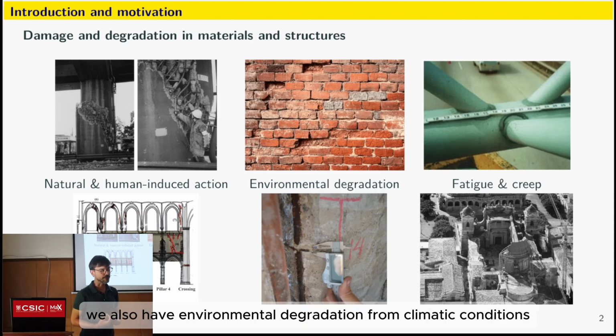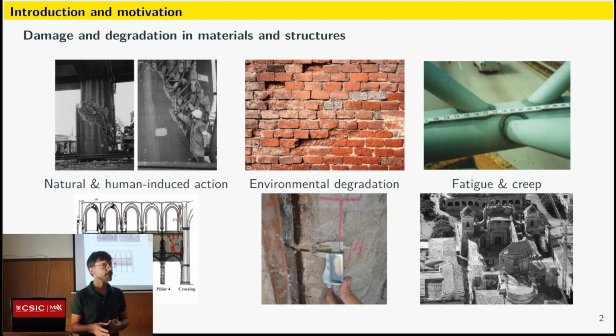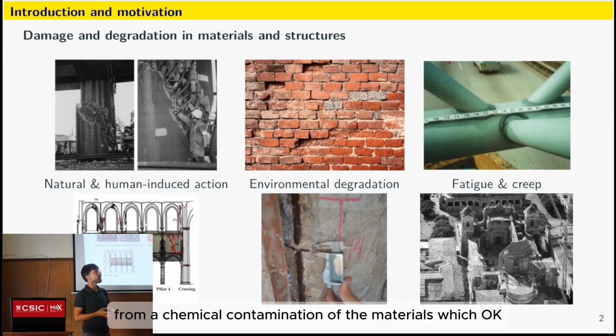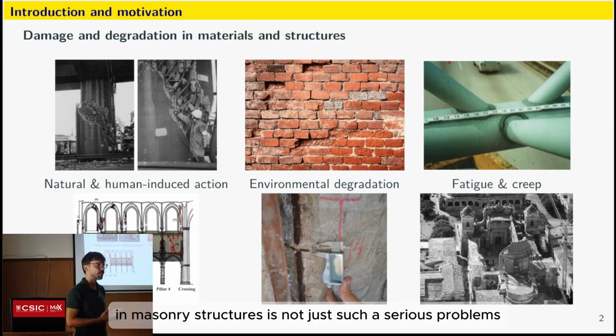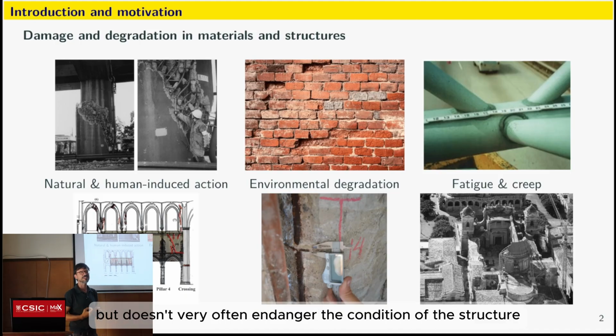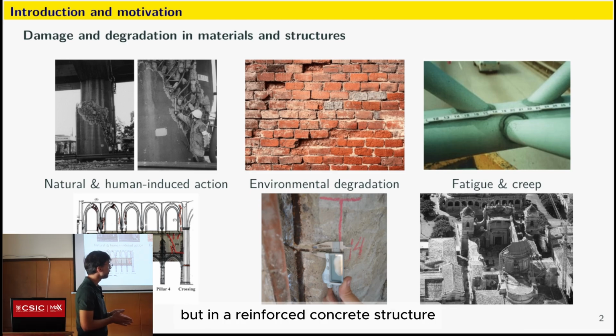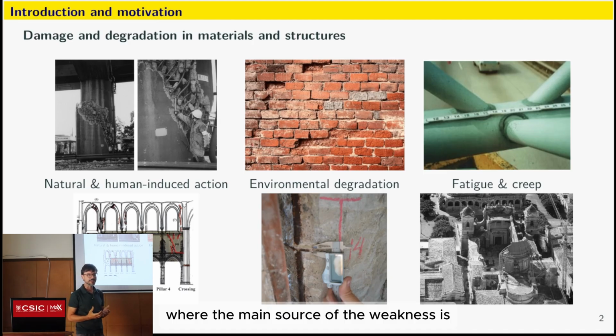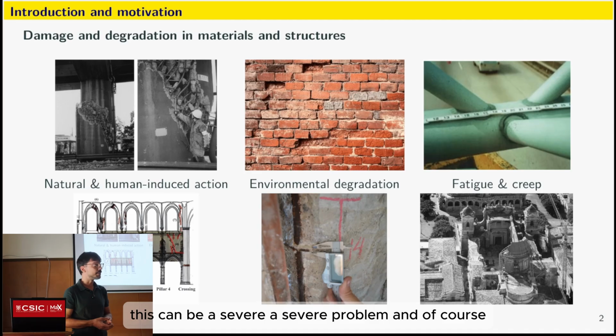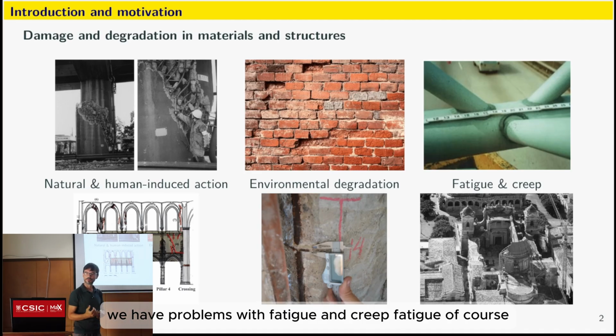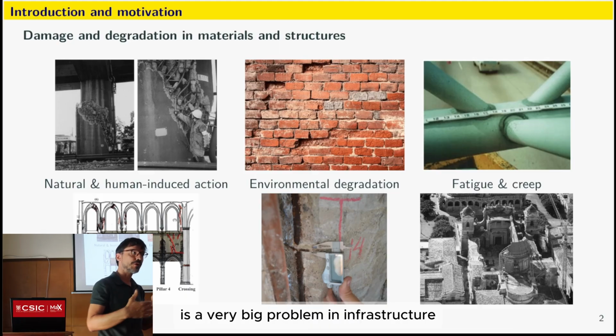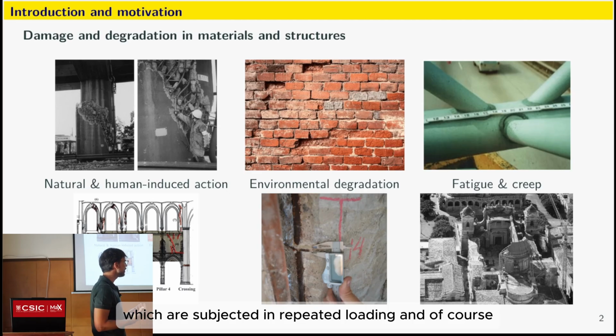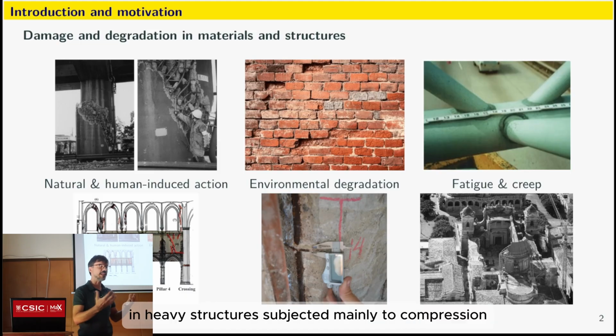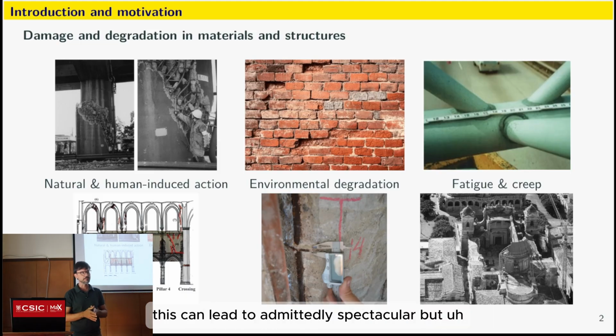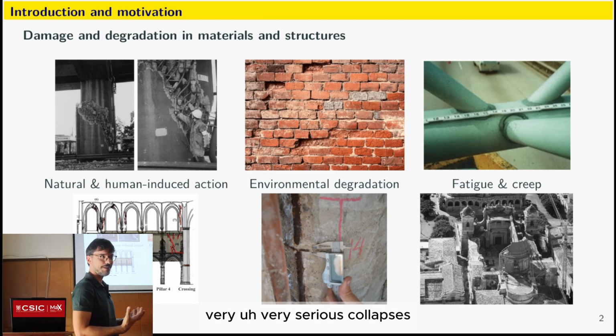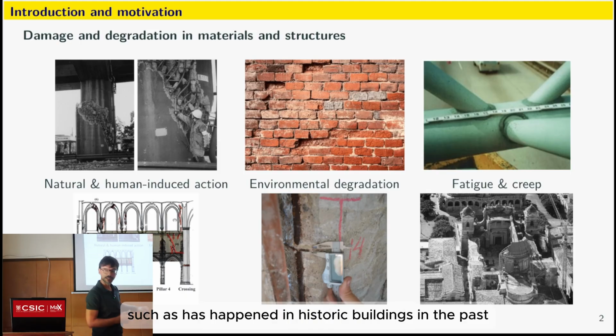We also have environmental degradation from climatic conditions, from pollution, from chemical contamination of the materials, which, in masonry structures, is not such a serious problem. It can cause superficial degradation, but doesn't very often endanger the condition of the structure. But in a reinforced concrete structure, where the main source of the weakness is, of course, the reinforcement, this can be a severe problem. And of course, we have problems with fatigue and creep. Fatigue, of course, is a very big problem in infrastructure, mostly in bridges, which are subjected to repeated loading. And of course, creep in historic structures, in heavy structures, subjected mainly to compression. This can lead to admittedly spectacular, but very serious collapses, such as has happened in historic buildings in the past.